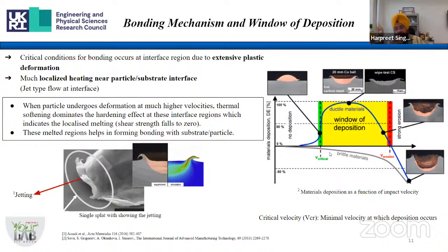Now, as we go through this, we can understand that one of the requirements for our feedstock particle is that it should be ductile, because we are talking about plastic deformation, right? If your particle material is brittle, then we can expect that we will not be getting a very nice coating. So that is one comment from this side. Another thing is this very nice schematic, which shows the deposition efficiency of cold spray. Which means that suppose you are pushing 1 kg of powder towards the substrate, how much of it is going to stick on the surface, and that ratio will give you the deposition efficiency here.